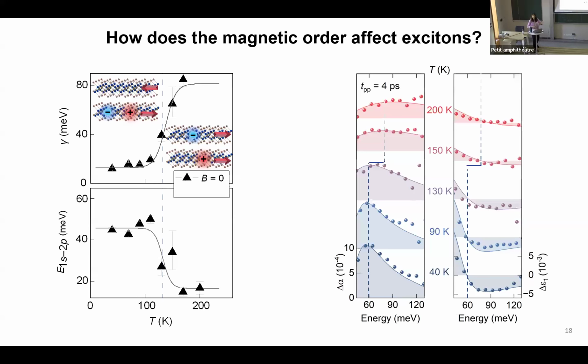On the other hand, this delocalization is generating a simultaneous effect on the broadening or scattering factor. We see that across the Néel temperature, the broadening literally increases by an order of magnitude. So we have a transition from quasi one-dimensional excitons to rather three-dimensional excitons above the Néel temperature.